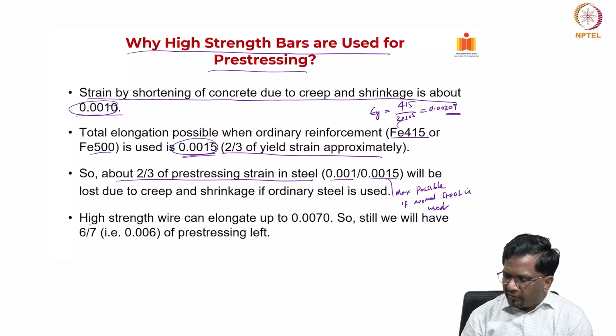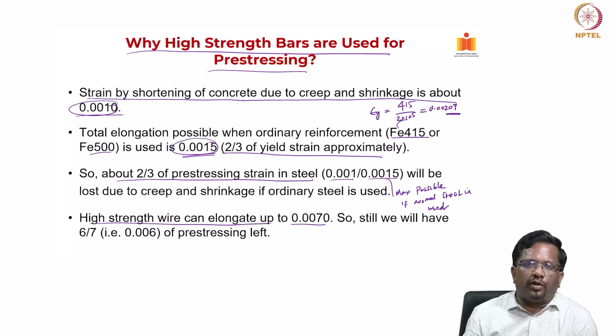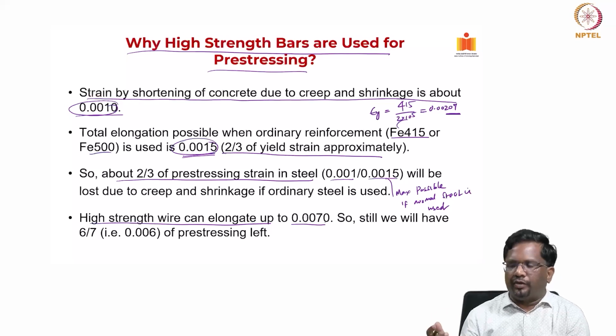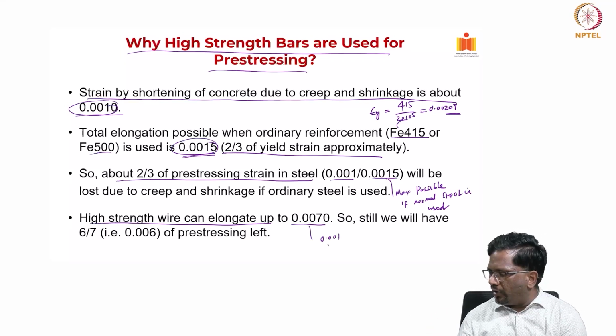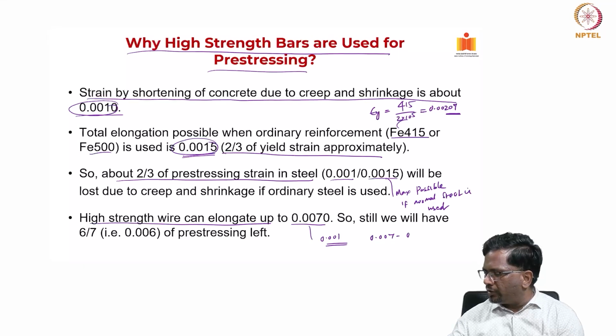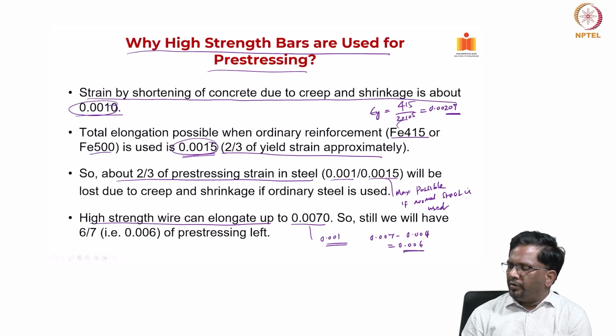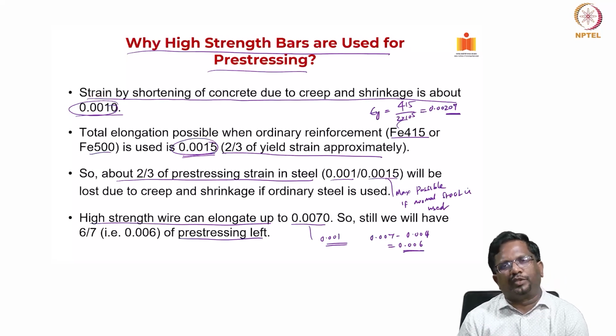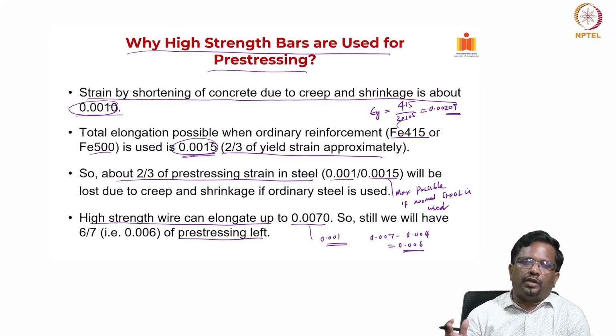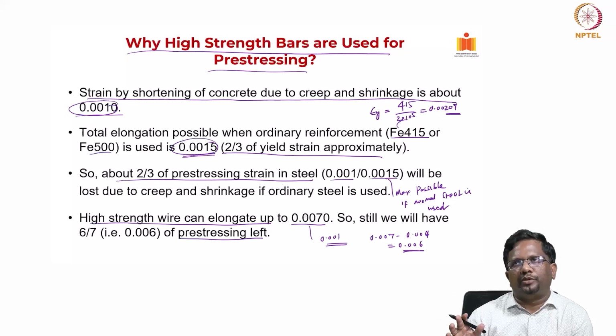Now, if I use high strength wire, we can go as high as 0.007 for the initial prestressing. Even if 0.001 is lost, I will still be left with 0.007 minus 0.001, which is 0.006. So we will still have 0.006 of prestressing, which is quite effective for putting compression on the concrete. That is the reason you have to go for high strength prestressing steel. If you use regular normal steel, you cannot apply too much strain, and most of it will be lost due to shortening of concrete from creep and shrinkage. That is why the early attempts at prestressing were not successful.